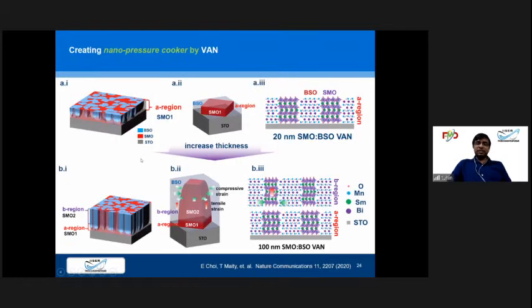So this is the schematic diagram. This is our thin film like that, so there is no strain. There is only a little bit of strain from the substrate, but no out-of-plane strain. As we increase the thickness, the substrate also starts giving compression, and the tensile strain also comes into play. We confirmed it because there is no difference between the thinner matrix film and the plain film. But as we increase the thickness of the matrix film, we get a different kind of physical properties.